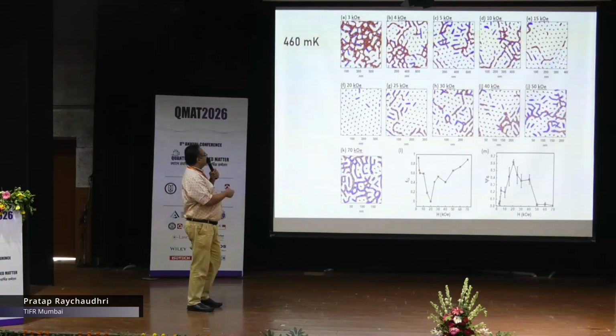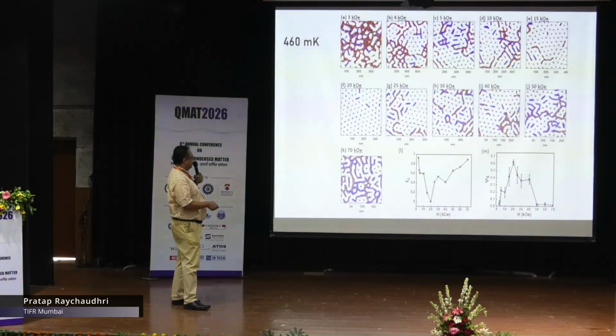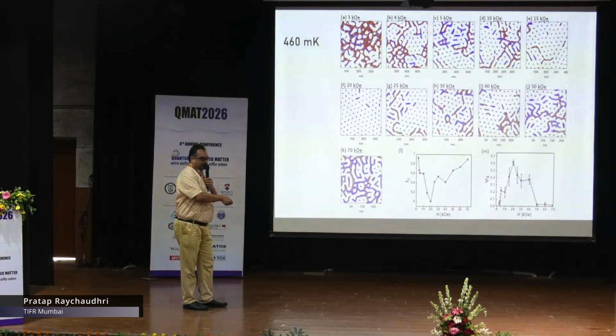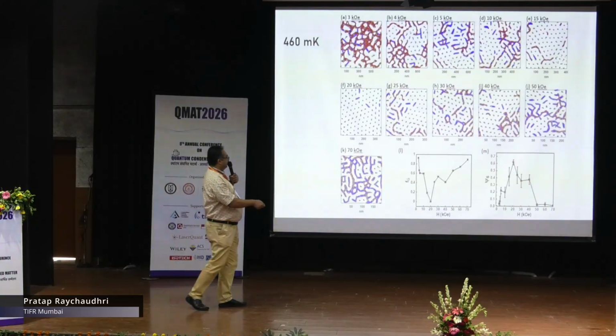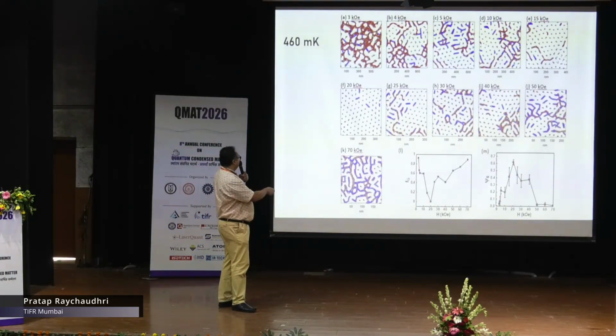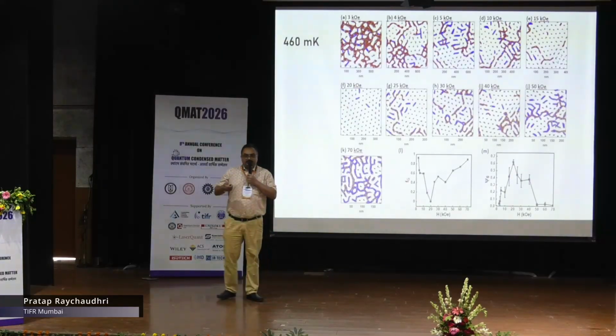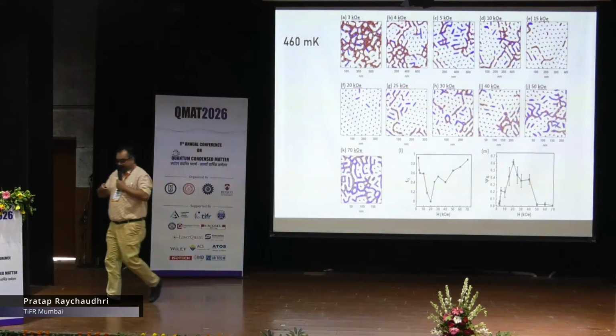You can do various metrics. You can look at the number of vortices that are connected to motion path. Here it's almost, this fraction is 100%. It comes down to 0 at 20 kOe, then again increases to 1. You can also look at the metric of orientational order, psi 6, and you can see this is completely disordered. It gets maximally ordered here at 20 kOe and comes down. Alright, but this is as a function of magnetic field.